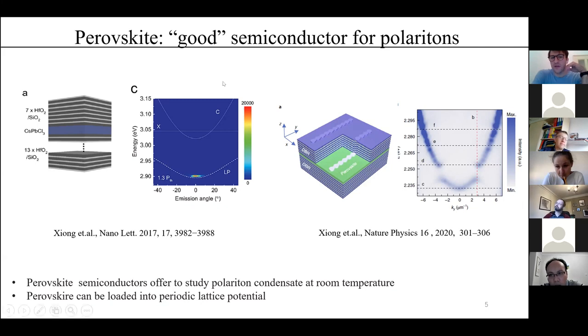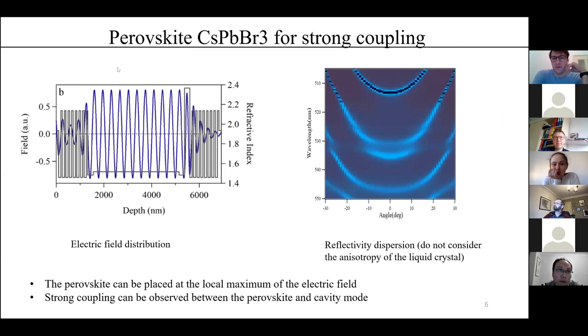So how does it relate to the wavelength of the condensate you observe? Is it blue shifted or red shifted, or is it near the energies of the condensate? So the exciton resonance in our model is like 2.4 electron volts. The lasing energy is around, sorry, here you can see it is 2.28 electron volts. It's smaller than I usually see.